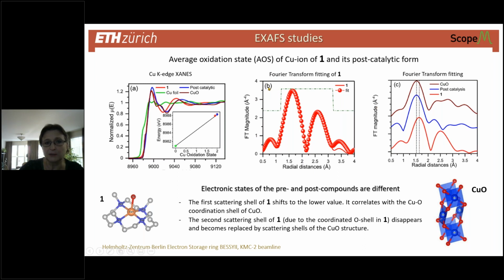Now, if you go to graph B, the Fourier transform fitting of compound 1, this red curve is presented here, and it gives a few scattering shells, a few features that we can then follow in the Fourier transform fitting of the post-catalytic compound. This graph shows exactly what I'm speaking about. Red is the Fourier transform fitting of compound 1, and blue is the same for the post-catalytic compound, and the reference is the copper oxide phase. You see already that the first scattering shell shifts to lower values in the post-catalytic compound. And it correlates pretty well with the coordination shell of copper oxide here.